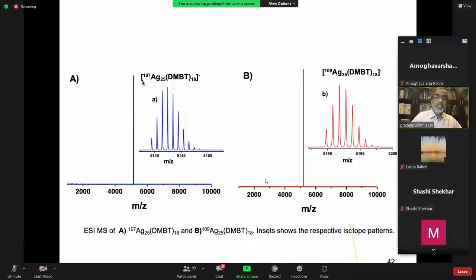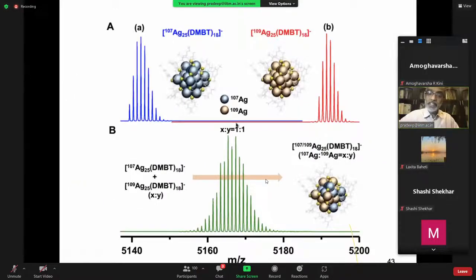So we produced this cluster with 107 silver, having a mass number like this, 5142 is a peak that you can see here. And this is another cluster, the 109 cluster. The difference will be 50 mass units. It is 5192. And you mix these two. These are two separate solutions that we have. And Papri did this very interesting experiment. Here is this cluster. Here is the other cluster, 107 and 109.